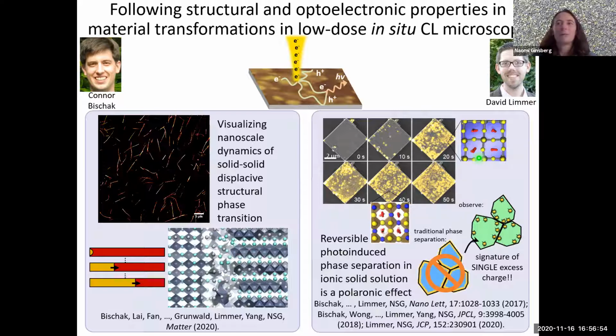So before we imaged this process, it had been envisioned as a sort of traditional phase separation with two macroscopic phases. And I think it's really cool that when the material is illuminated, the spots that don't light up look just like they would in the dark, but right next door, the charge alters the material composition and structure to make this little nano beacon, thanks to pretty substantial electron-phonon coupling.